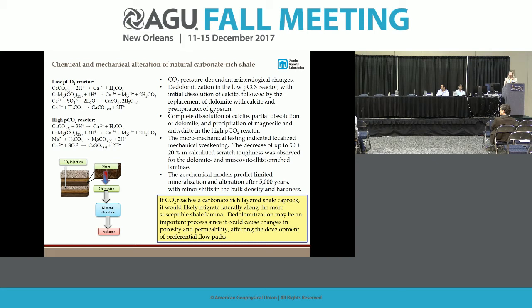So overall conclusions are that the reactions triggered by the injection of CO2 are pressure dependent, and we see different products at the end, depending on the pressure of CO2. So again, it's a pressure-dependent reaction. We observed dedolomitization in the low pressure CO2 reactor, and we think that the dedolomitization process can actually be important for CO2 performance because it has been observed at natural sites that are analogous to CO2 storage, where CO2 is actually seeping from the underground reservoir.